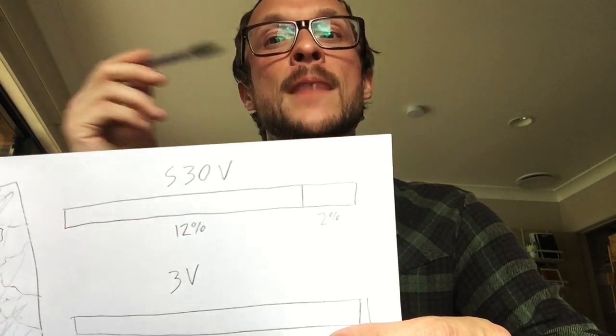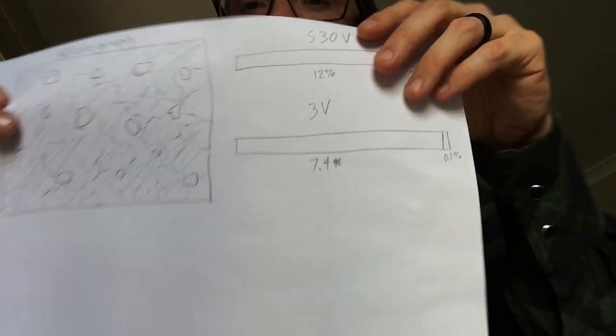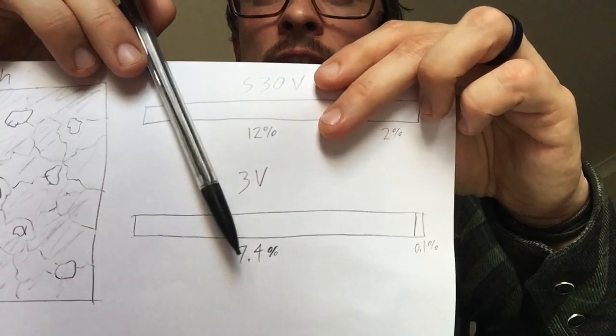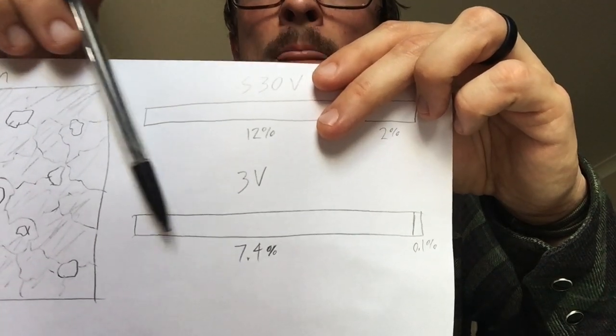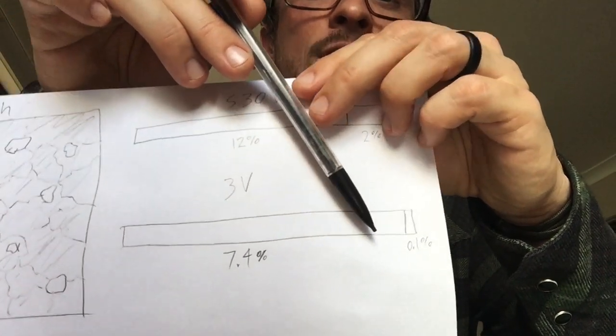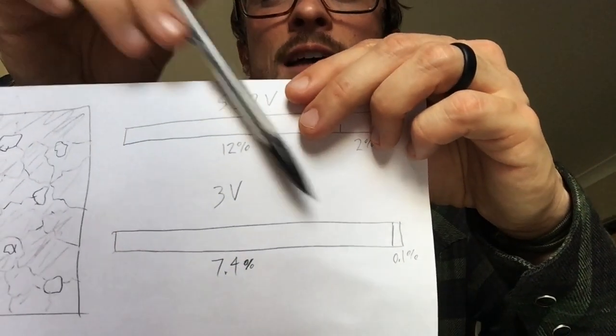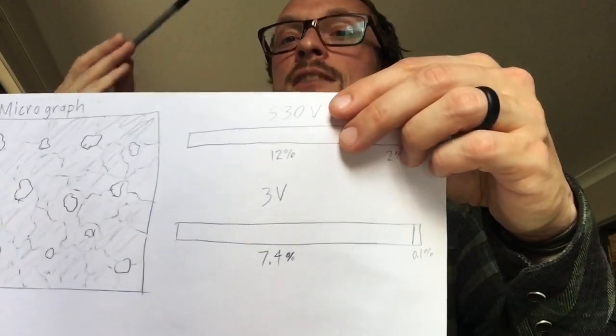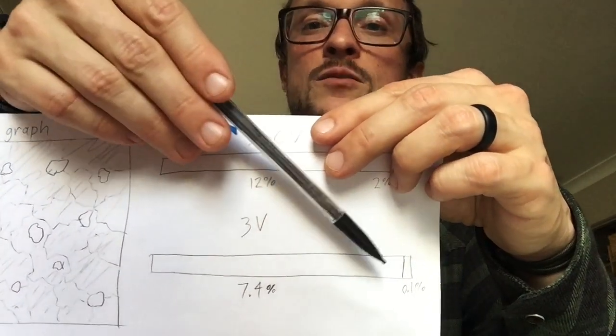And so the extra 2% is actually counteracting your toughness, counteracting your rust resistance, and not helping that much with your wear resistance either. So your options in the past have been to cut a bunch of chromium out of the mix so that the small amount of chromium that's left wants to stay in the solution, or in the matrix. That's what they've done with steels like CPM 3V. It's got like 7.5% chrome overall, but a large amount of that, I don't even know how much, is going to stay in the steel matrix to help with rust resistance, and a very small amount is going to be converted to carbide and thereby decrease toughness.